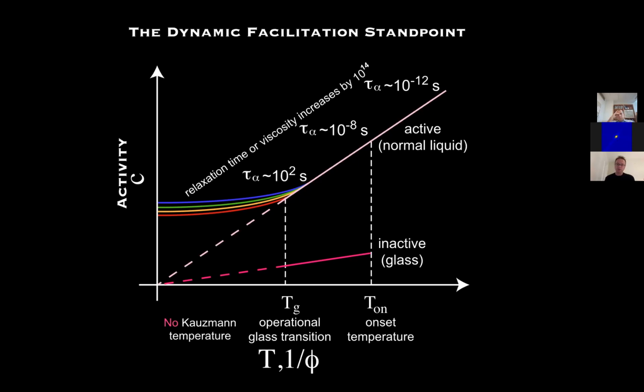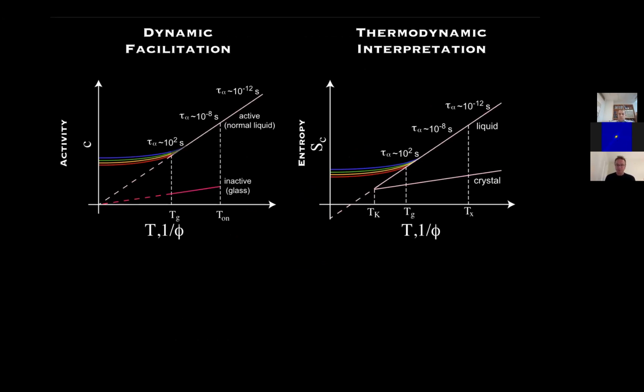And remarkably, the best data that we have cannot really tell the difference between these very different standpoints for explaining the glass transition. So just to recap, there's the dynamic facilitation picture I've just shown on the left, and the thermodynamic interpretation has this Kauzmann temperature where the liquid and crystal branches of the configurational entropy would meet, and that is entirely absent in the dynamic facilitation picture. So what I want to address in this presentation is which of these is the correct interpretation.